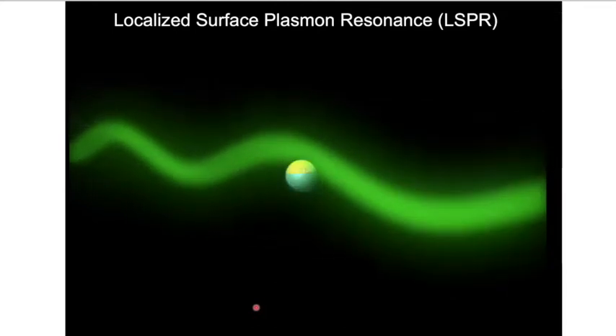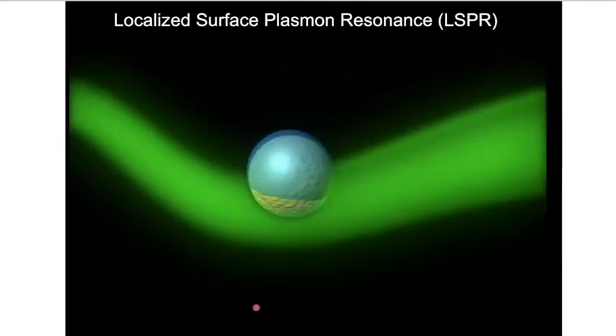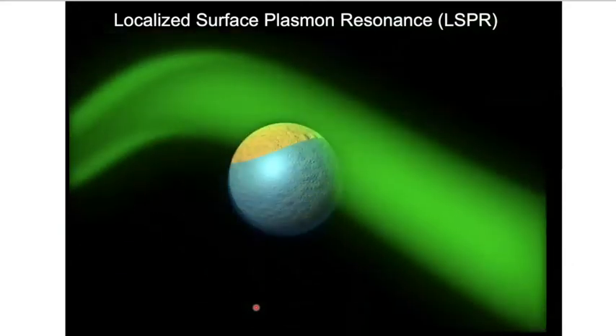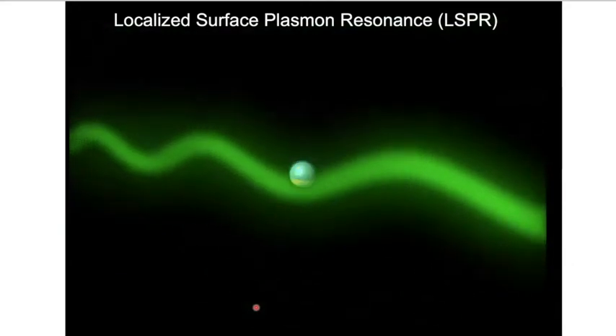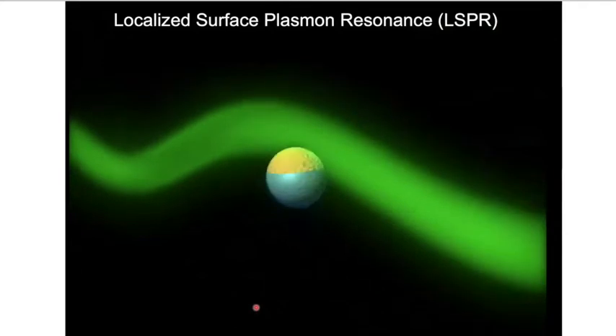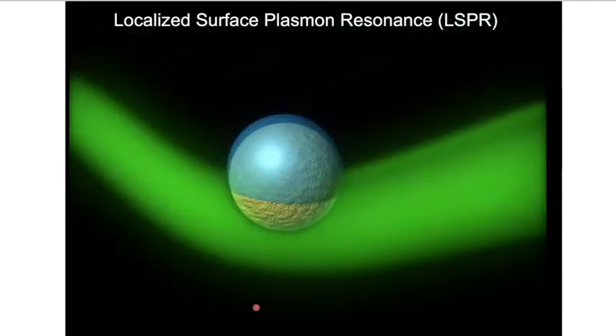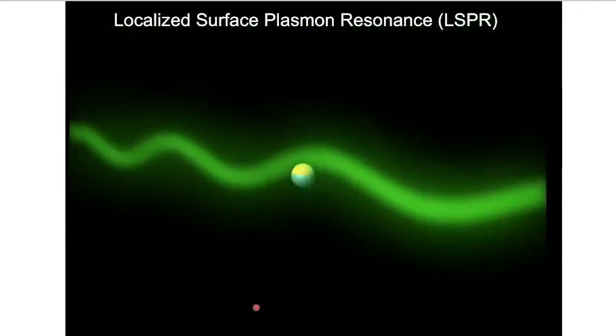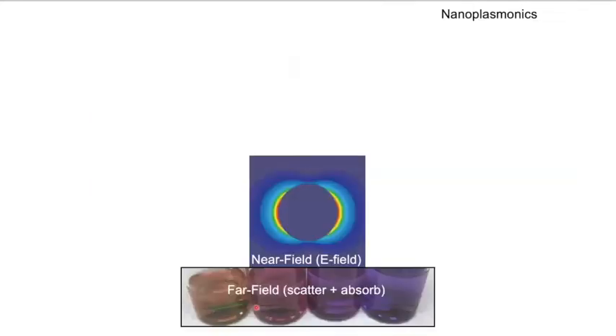you can then get huge enhancement in this resonance, and you get an amplification of the electric field at the surface of the particle, as well as greatly enhanced light absorption and light scattering. And that creates color, right? This is wavelength dependent absorption and scattering. It creates color in the far field. In the near field, what I'm going to talk about when I say near field is really this near field enhancement of the electric field.